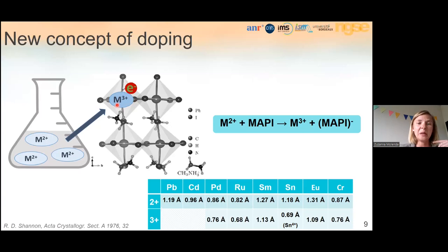So I developed a two-step doping approach: first spin-coat and anneal the perovskite, then spin-coat samarium iodide and anneal again. The conductivity of samples prepared this way increased by around two orders of magnitude compared to undoped layers. As a control, I measured the conductivity of samarium iodide alone to confirm the increase comes from the combination of perovskite and dopant. By scanning different doping concentrations, I reached around three orders of magnitude conductivity increase, and the method was very reproducible.